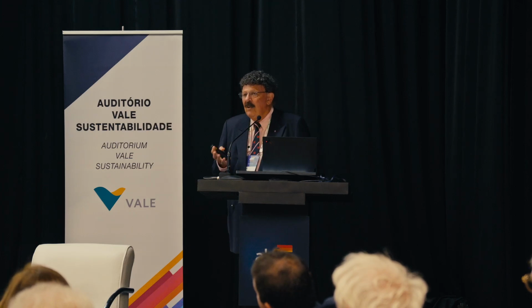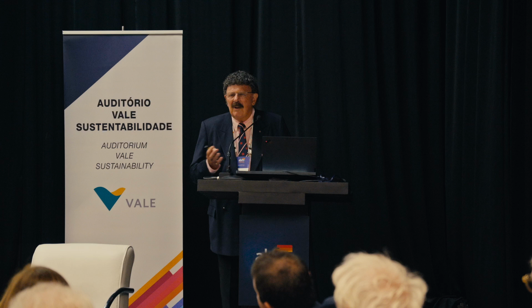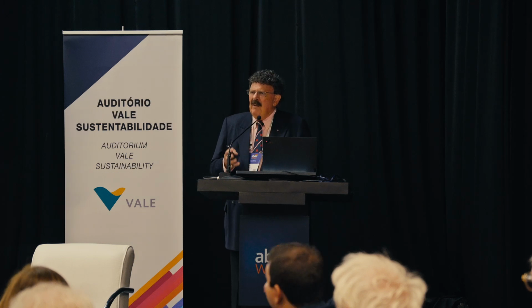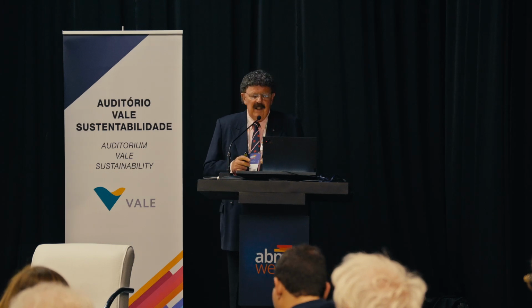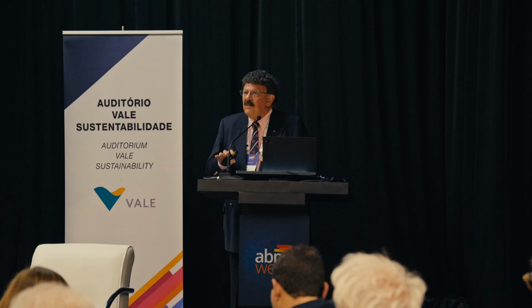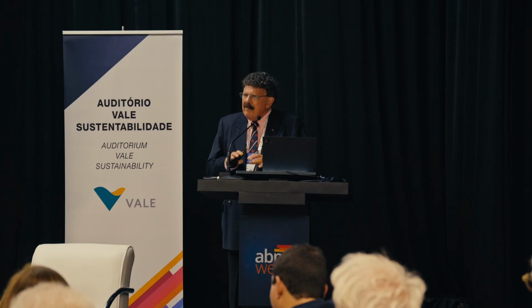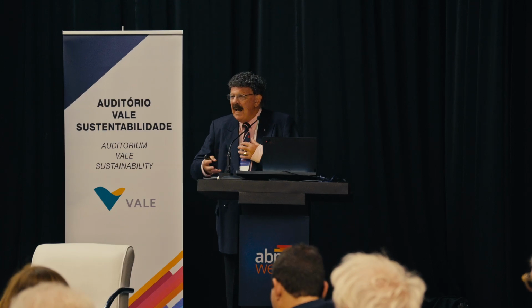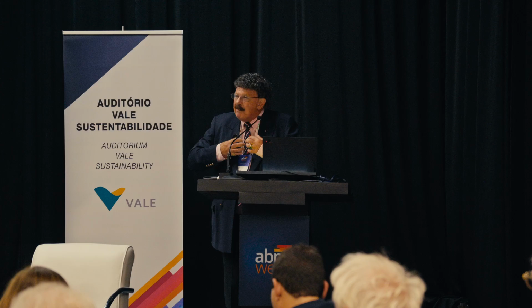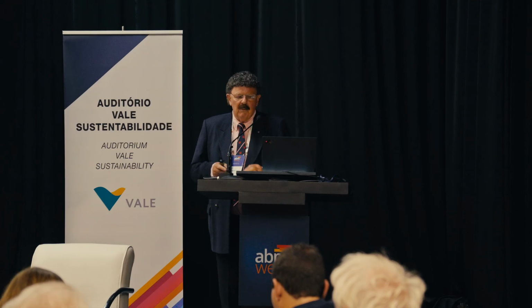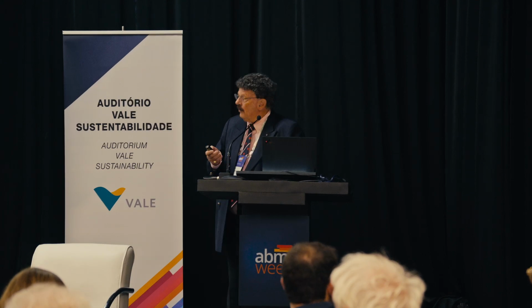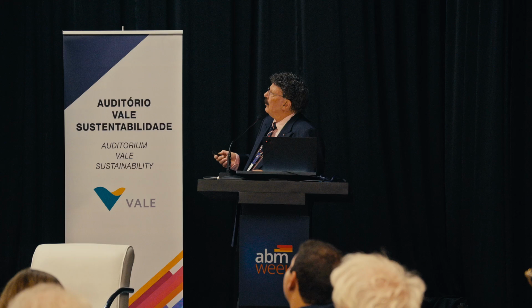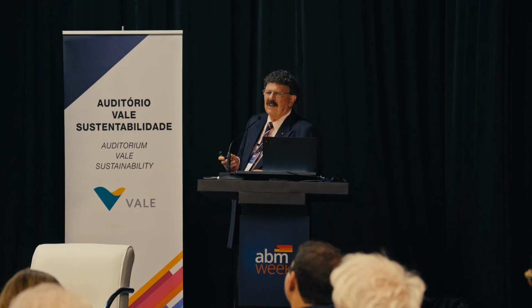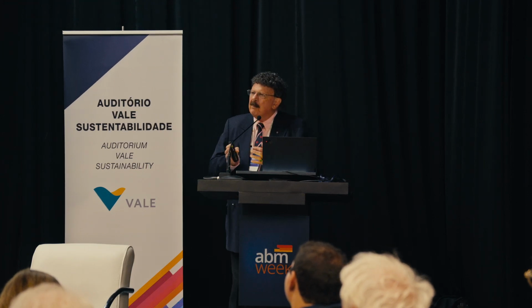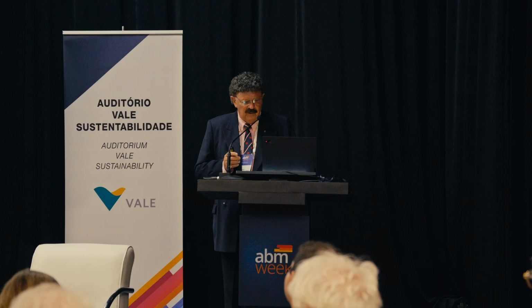Now, kink bands are unusual. They were first mentioned by Orowan in the 1950s. Very little work has been done on kink bands. And these, we think, are the reasons these alloys are so tough. Kink bands promote instability, necking, but they don't here. They promote deformation and move it away from the crack tip. And of course, at very high temperatures, the materials basically recrystallize. So there's work to be done to push the temperature a little higher. There's no question about that.